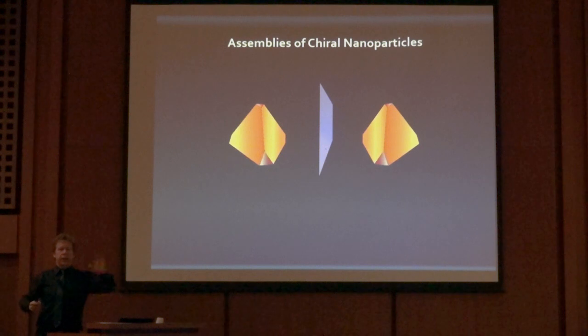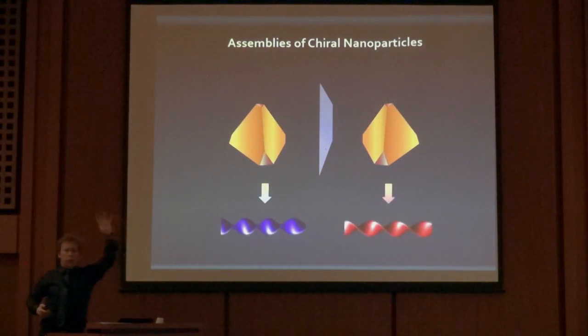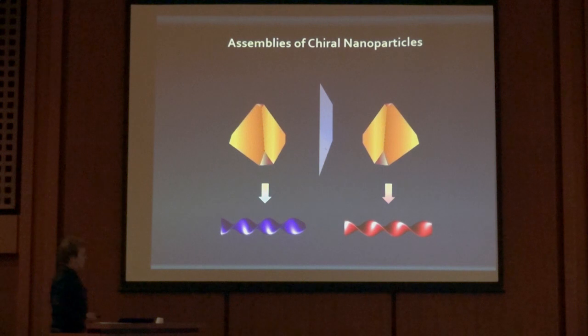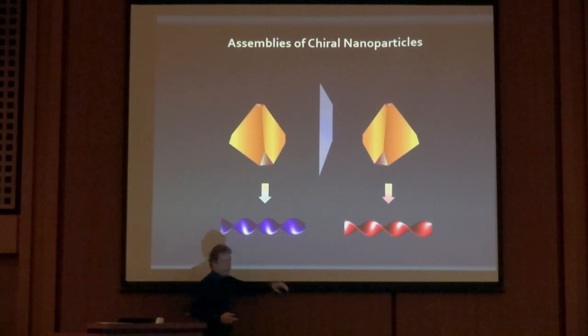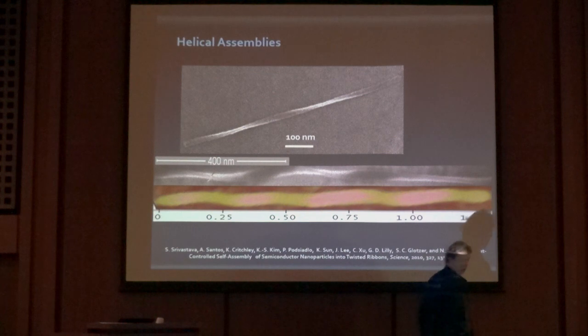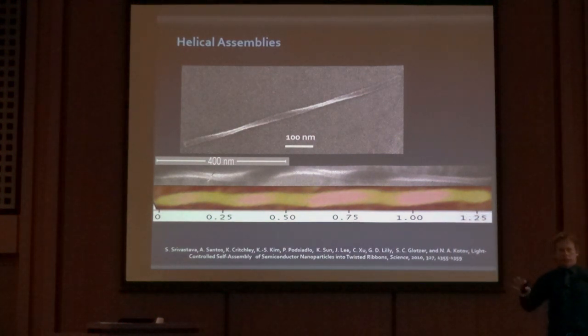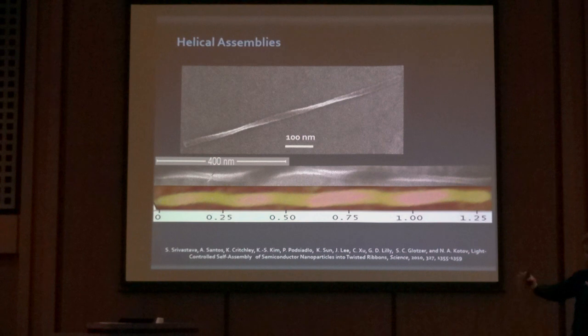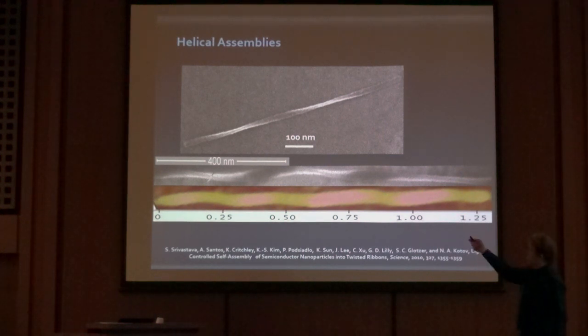Quickly, about assemblies of the chiral particles. If we're talking about asymmetry, we have to look at the assemblies of the chiral particles in this kind of helical structure. Not a lot of new concept, the same. So van der Waals interaction, electrostatic repulsion, as soon as we slow them down, as soon as we reduce electrostatic repulsion, the particles form this chain-like, or in this case, fibril-like or twisted ribbon-like structures.